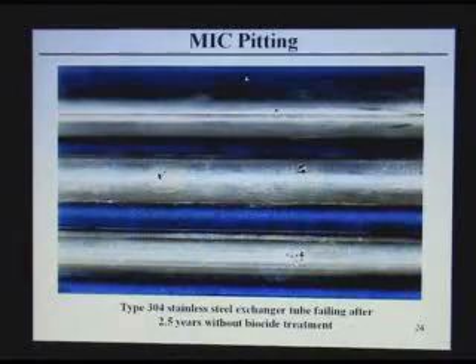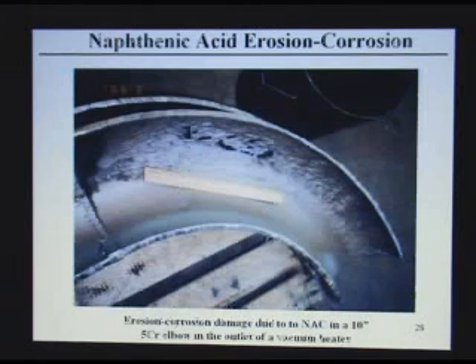Some microbes like to eat nickel, and corrosion starts from inside, and you end up with a pinhole, like this stainless steel tube in a heat exchanger. So you end up with holes, and the rest of the pipe is sound, but where the colony was, there is the corrosion. This is corrosion by naphthenic acid.